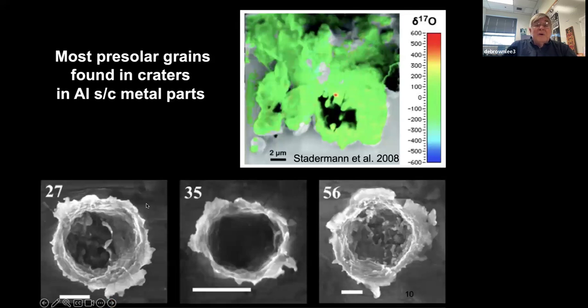Most presolar grains that were found in the comet sample were found in craters. Our main collection medium was silica aerogel, but it was held - the aerogel was like ice cubes held in an aluminum frame. And it turns out the craters were the best places to look for presolar grains because the material was highly concentrated in the liners of these impact craters.